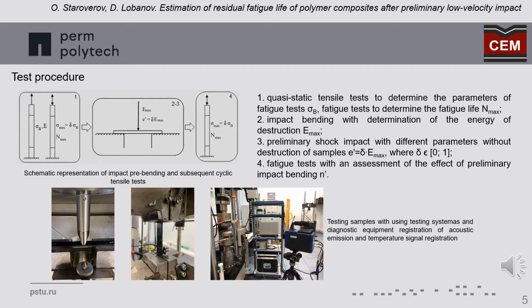The nominal fatigue life Nmax is obtained from a test with the parameters of the maximum stress in the cycle sigma max 0.75 sigma b, the asymmetry coefficient R 0.1 and the frequency 20 Hz. During the cyclic test, the frequency and amplitude of the loading were selected in such a way that the heating of the sample did not exceed 20 degrees Celsius relative to the temperature at the beginning of the test.